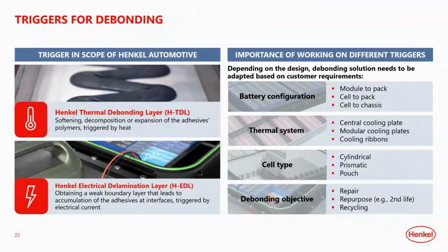So there are two primary debonding mechanisms we see as optimal for the automotive space. One being the electrical delamination that was demonstrated in the video, and the other being thermal delamination or debonding. Thermal debonding is selected as a best option for some components within the vehicle, and it utilizes the application of localized heat to the bond line of the debondable adhesive, which basically softens the material, causes it to foam, and makes it easy to pull apart or disassemble.